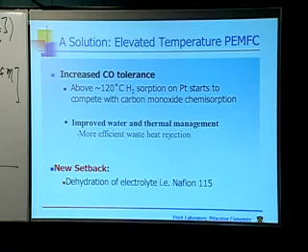It also turns out that the free energy for binding of hydrogen to platinum is pretty temperature invariant between room temperature and up to actually 200 degrees C, whereas the binding of CO to platinum, that free energy of binding is falling off very nicely above 100 degrees C. So right around here, you start to win, sort of. And if you could run a little hotter, maybe 130, 140 degrees, you can win even more. That's sort of a magic number.